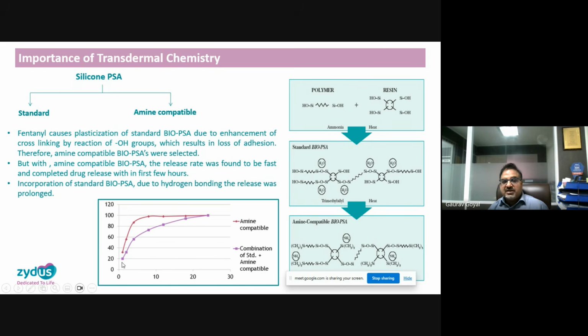So to get the combination, we have used the combination of standard and amine compatible. Amine compatible we use to get the release profile, and standard bio-PSA we use to get sufficient solubility of fentanyl in the silicone polymers. So this is one of the reasons we have used the combination of standard and amine compatible silicone pressure sensitive polymers.